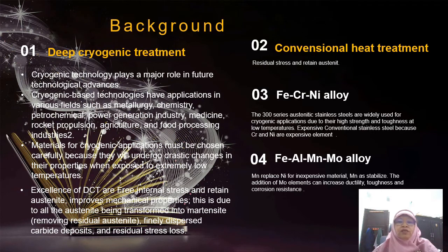This is due to all the austenite being transformed into martensite, removing residual austenite, finely dispersed carbide deposits, and residual stress loss. Disadvantages of conventional heat treatment are residual stress and retained austenite. The 300 series of austenitic stainless steel are widely used for cryogenic applications because of their high strength and toughness at low temperatures. These alloys generally contain chromium 18 to 21% and nickel 9 to 14%.